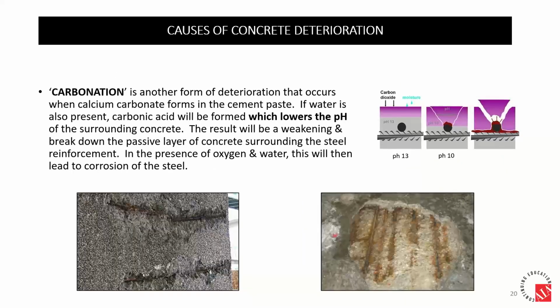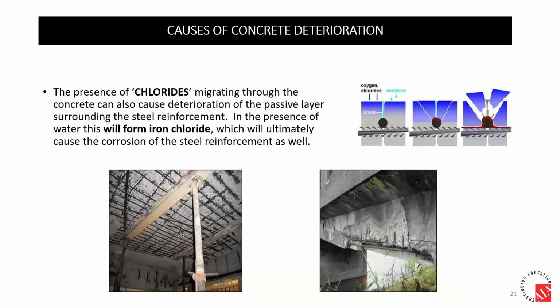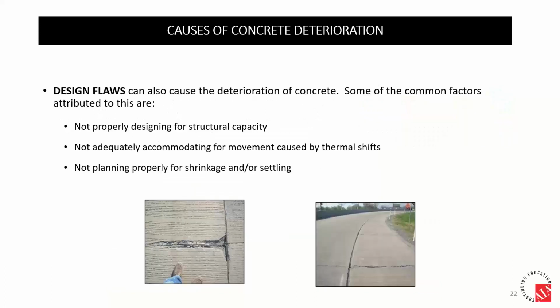Carbonation is the presence of carbonic acid, which lowers the pH, which again is going to result in the same thing as rusted rebar and spalling. Chlorides have the same effect. Again, rusted rebar and spalling.